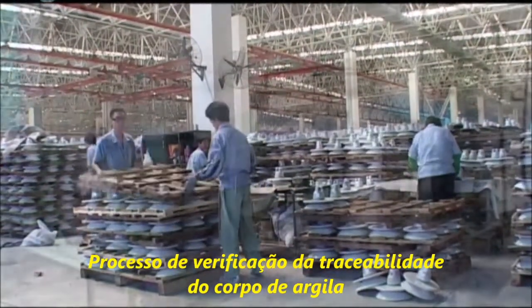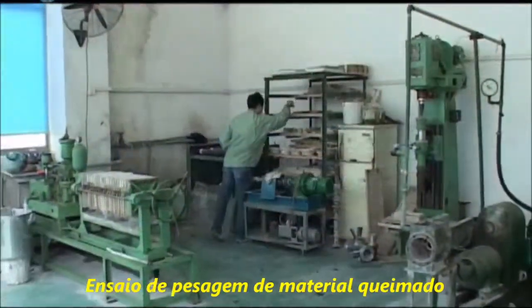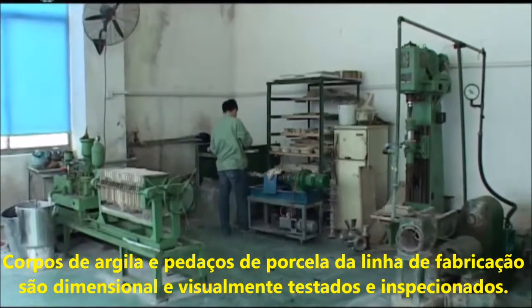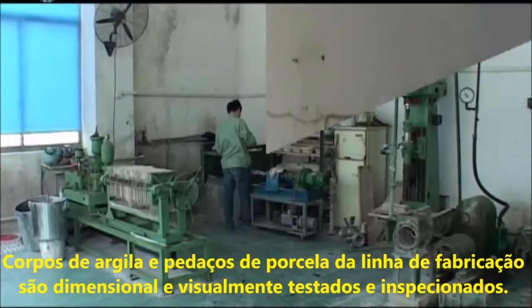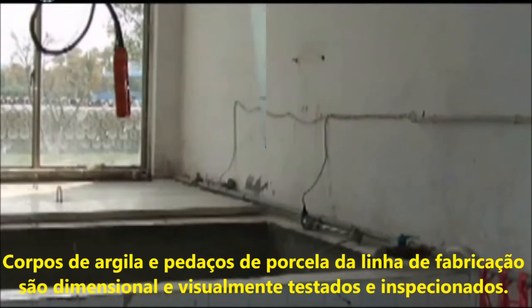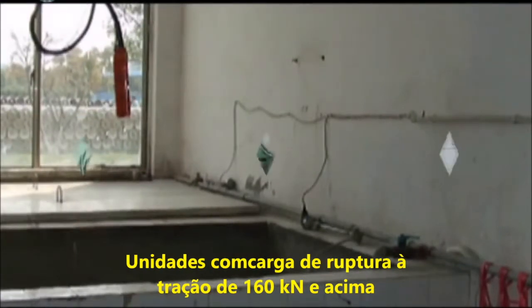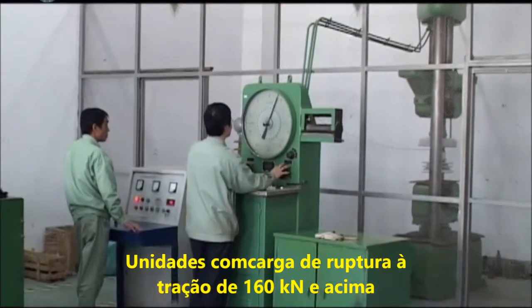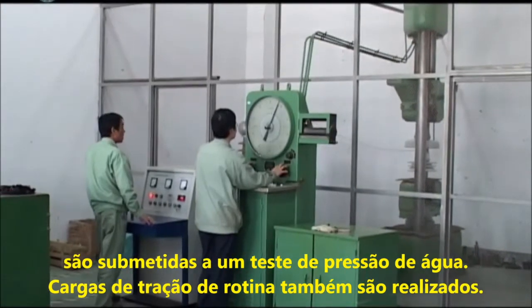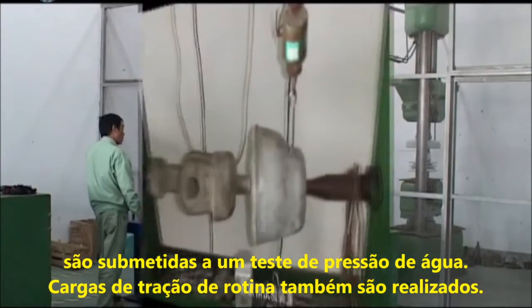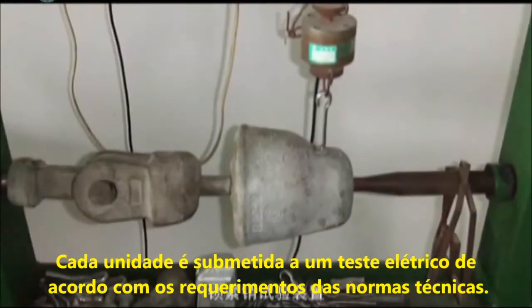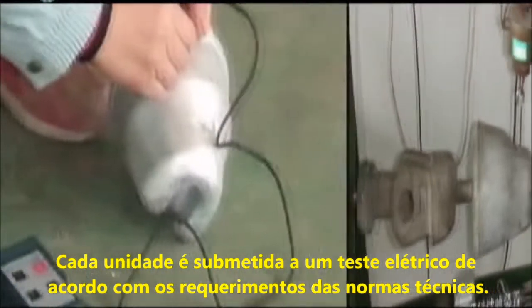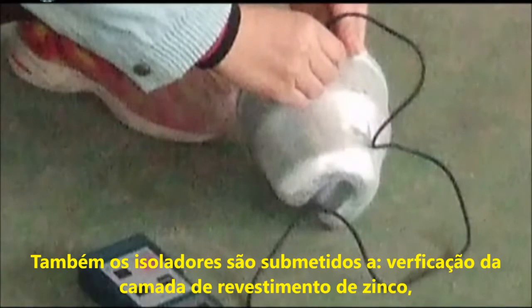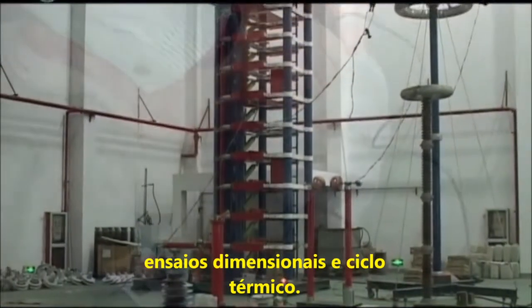Process of mud index test. Firing scale test, blank test, and porcelain pieces are visually and dimensionally inspected. Units with ratings of 36,000 pounds and above undergo a water pressure test. Routine tensile loads are conducted. Each unit receives standard electrical testing as required by standards. Additionally, spot checks are conducted for appearance, dimension, and temperature cycling tests.